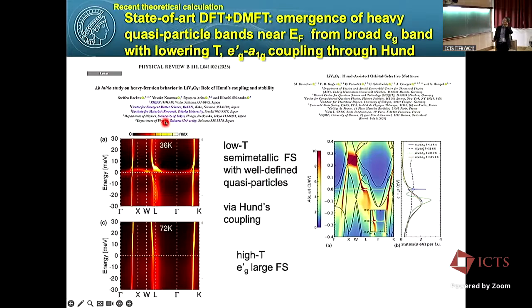And at the end of the day, I came to my theory colleagues and showed them the data. And they did state-of-the-art DMFT calculation. So Arita updated his technique. And two groups, the group of Arita and Antoine Georges, both reproduced that. This is 10 millielectronvolts, so very narrow, okay? A miniature of the LDA band around the Fermi level, showing a small Fermi surface in the metallic state, okay? Consistent with what we observe.